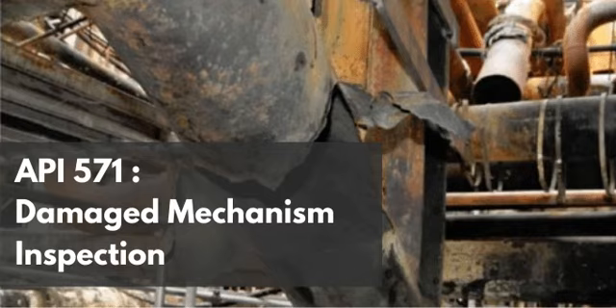Right. The higher chromium ferritic stainless steels. The dangerous ones. Yes. The text points out that these are much more susceptible, and it defines the exact chemical makeup that pushes them into that danger zone. Which grades are we talking about here? We are talking about type 430 stainless steel, which contains between 16% to 18% chromium. Okay, 16 to 18. And then there's type 446 stainless steel, which contains a massive 23% to 27% chromium. Wow. 27% chromium is a huge amount of alloying element to just have sitting in the matrix.